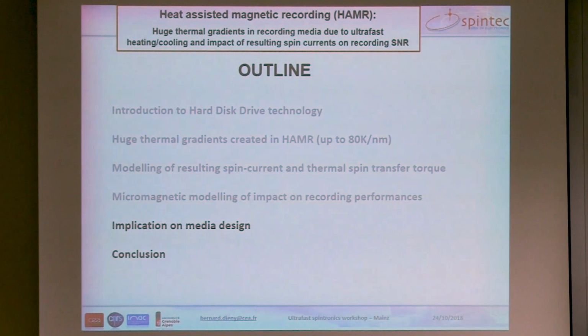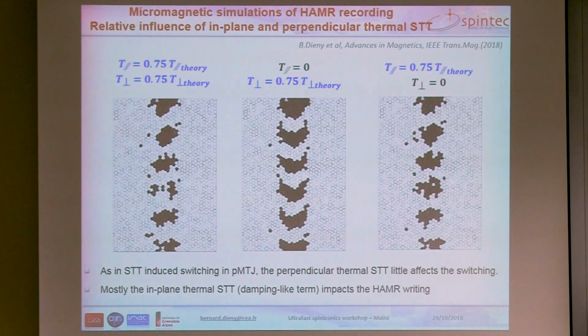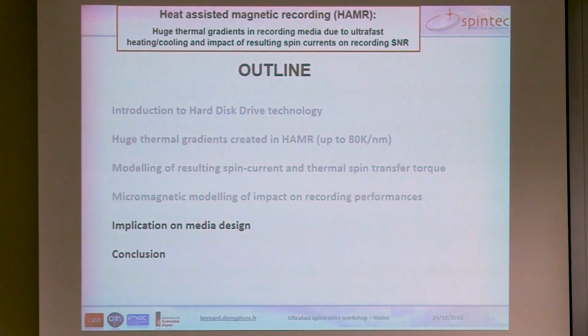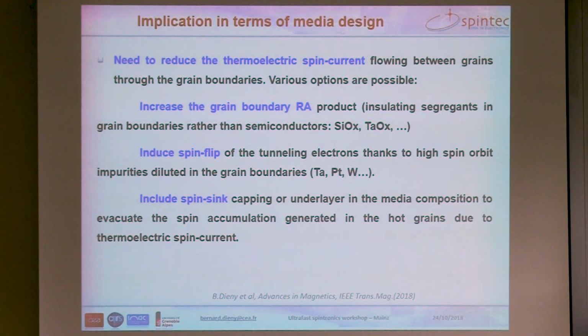But what does this mean in terms of media design? You understand from these kind of simulations that this huge thermal gradient and the associated spin caloritronics effect have a detrimental impact on the recording performance, because it tends to induce this anti-parallel alignment between the grains that are just in the process of cooling and the ones which are already cooled. So it means that somehow we need to limit the impact and do something on the media to limit the impact of this phenomenon. And so the general idea is that we need to reduce the thermoelectric spin current, which is tunneling across the grain boundary between the hot grain and the cold grain.